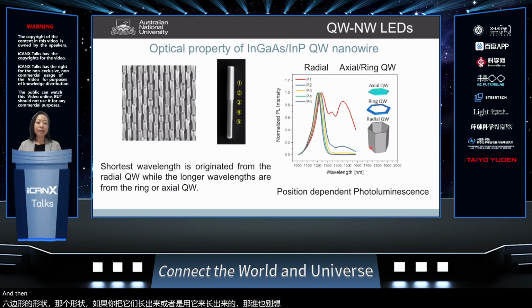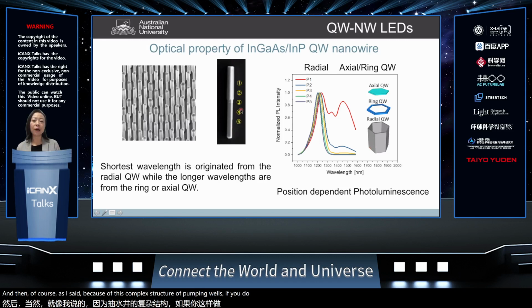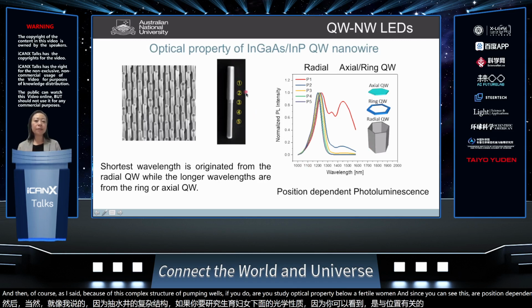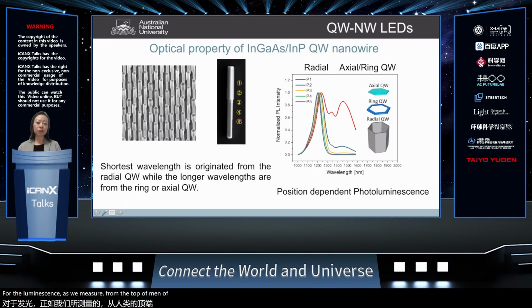And then, of course, as I said, because of this complex structure of quantum wells, if you study the optical property and do a photoluminescence, you can see this position-dependent photoluminescence as we measure from the top of the nanowire to the bottom of the nanowire. There's a change of the peak wavelengths, from the radial emission all the way to the axial emission. So this is from the bottom to the top here, this way. So it's basically consistent with our TEM results.